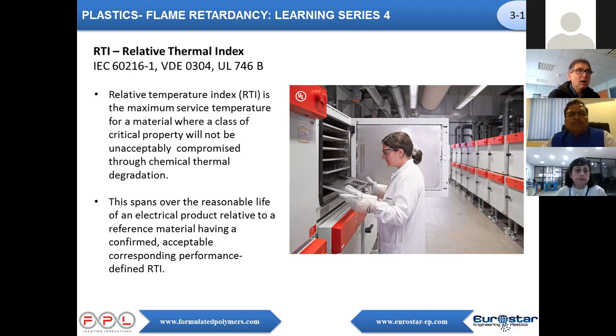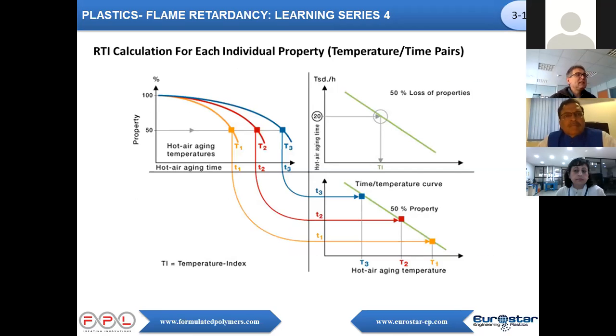So 60,000 hours means 7 years. So how is it done? It is done in ovens. So we are aging specimens in ovens, and at different temperatures. And from time to time, specimens are removed from this oven, and they are tested mechanically or electrically. This is what we see in this curve.